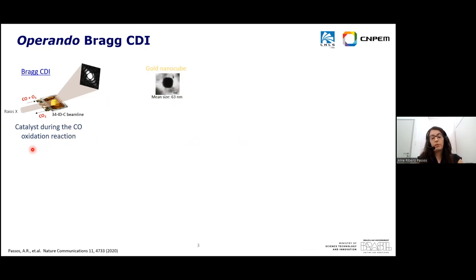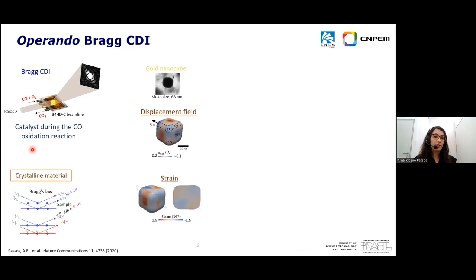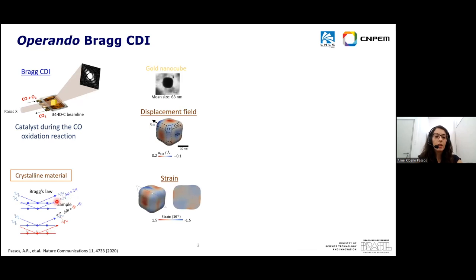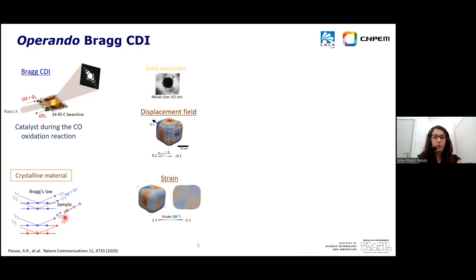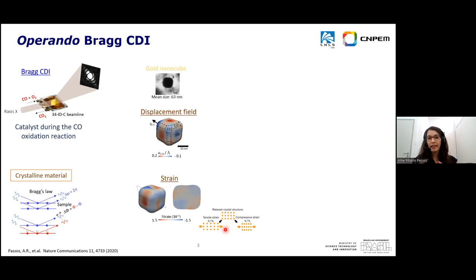CO oxidation is a model reaction but also an important reaction that happens in our cars every day. When we perform coherent diffraction imaging in Bragg condition, in addition to the 3D morphology, we also obtain the 3D distribution of the displacement field and the strain. In a crystalline material, X-rays are diffracted with a constant phase difference. When there is a defect, it produces a phase offset. Using phase retrieval algorithms, we can obtain the 3D distribution of the displacement field and calculate the strain. Strain is really important for catalysis because a strained region in a crystal affects the electronic properties — specifically the binding energy and the dissociation energy.